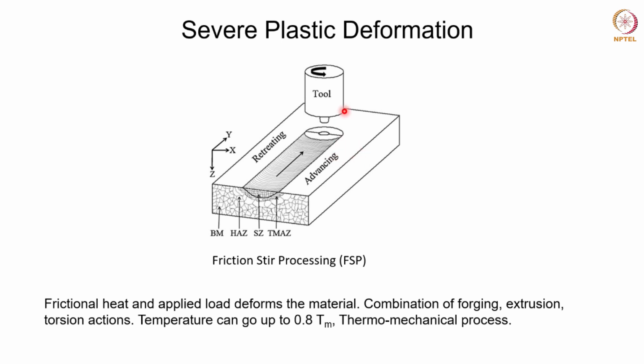And since a vertical load is also applied, once the material is plastic enough, once it is plasticized, then it will start to deform. And then as the tool is moved in a particular direction, like this, with a particular traverse speed, the material will be subjected to severe plastic deformation and it will be processed. So the material which is left behind the tool as it moves will be a processed material which has gone through severe plastic deformation and will have a finer grain size compared to the base material which is not subjected to any deformation at all.